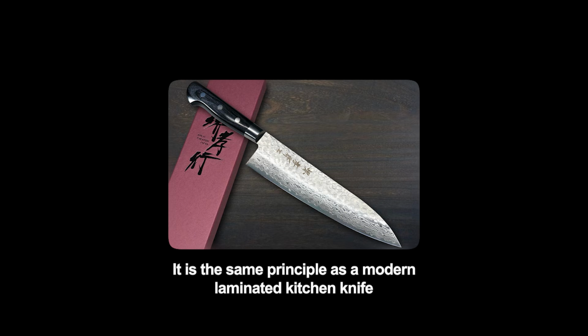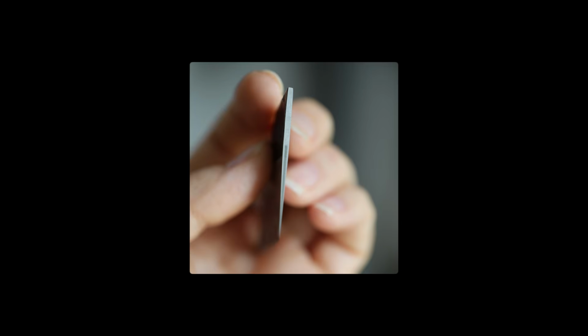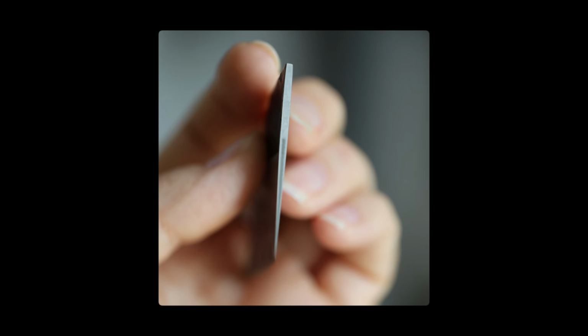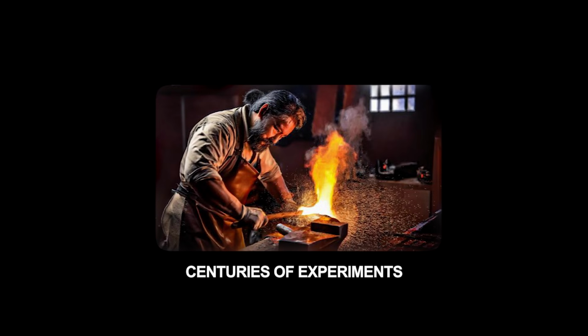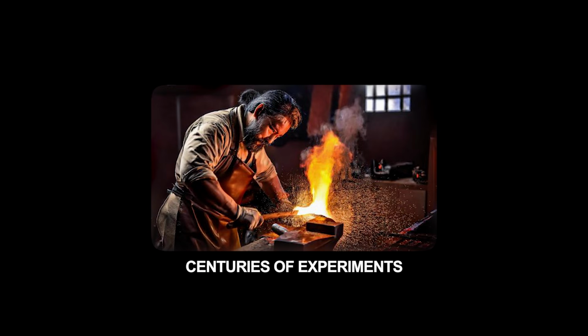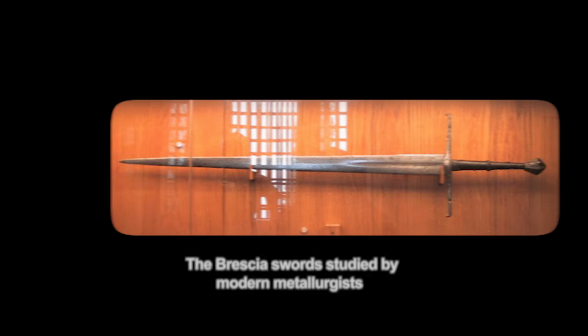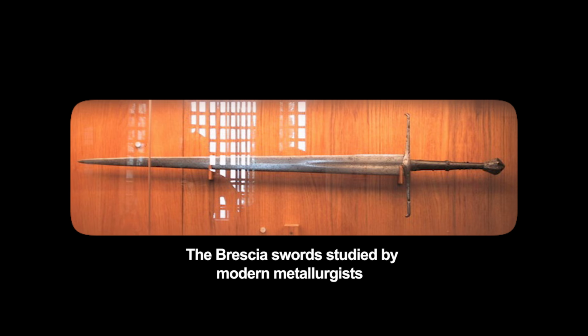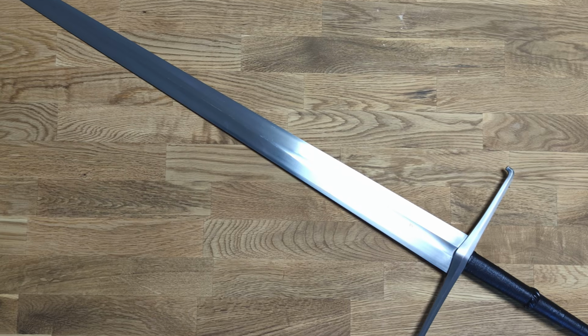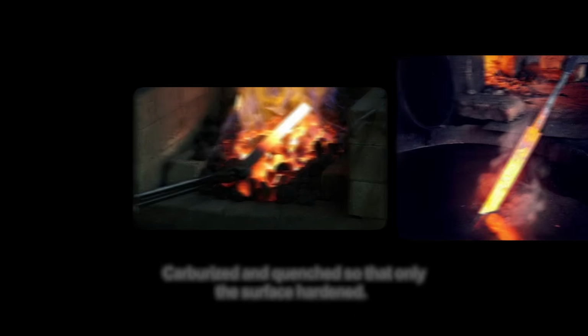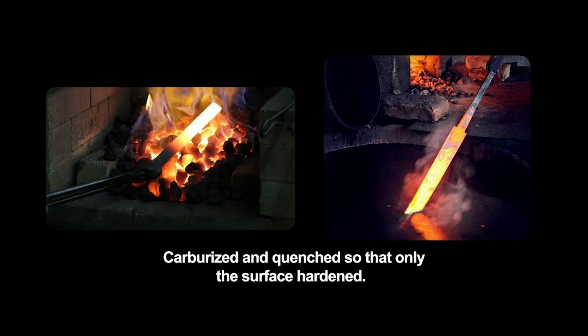It is the same principle as a modern laminated kitchen knife, where a hard steel core is sandwiched between softer steel cladding. Medieval smiths arrived at this solution through centuries of empirical experimentation. The Brescia swords, studied by modern metallurgists, showed blades of single steel or steel laminated onto iron, carburized and quenched so that only the surface hardened.